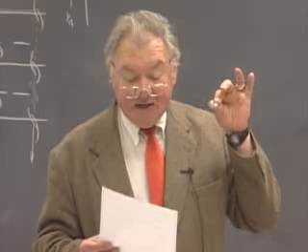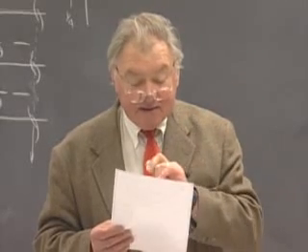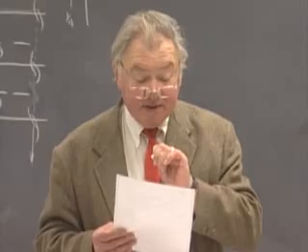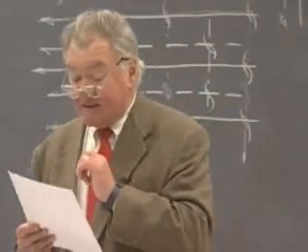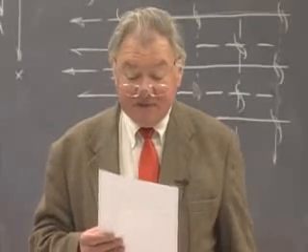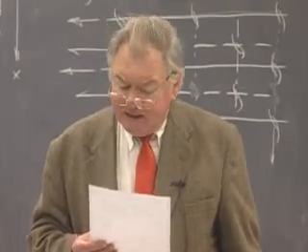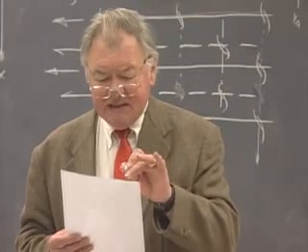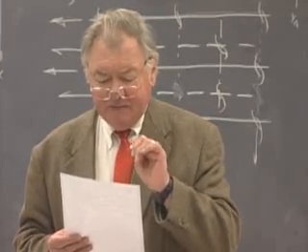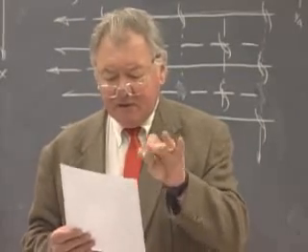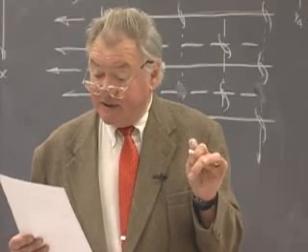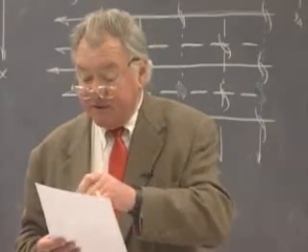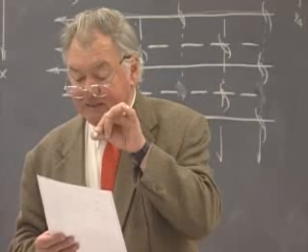If the C axis comes out of the plane of the paper, this then is a side-centered C lattice, and that is the capital letter symbol that appears first in the symbol for the space group. It is a side-centered lattice, and the extra lattice point is in the middle of the face out of which C comes. Then come in the space group symbol at upper left, this is the abbreviated form, Cmcm. And what I wanted to go over this example specifically for, there are 3 directions in an orthorhombic symmetry, no one any more or less special than any other. So if you look at the arrangement of symmetry elements, there's a 2 sub 1 screw axis coming out in the direction of C.